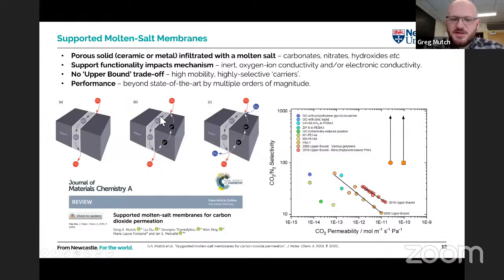And the reason for this is that the molten salt has almost infinite selectivity. There's about 3 orders of magnitude difference in solubility of carbon dioxide and nitrogen in the molten salt. And then it has extremely highly mobile carriers. These carbonate ions are in a liquid at 400 degrees, so they have very, very high diffusion rates. So high diffusion gives you high permeability and extremely high selectivity, up to around 1,000. So we're operating in this very interesting region here, where there's basically no other membrane materials that can operate. It's a very different way to build a membrane, and they're very new, very interesting, and very exciting.